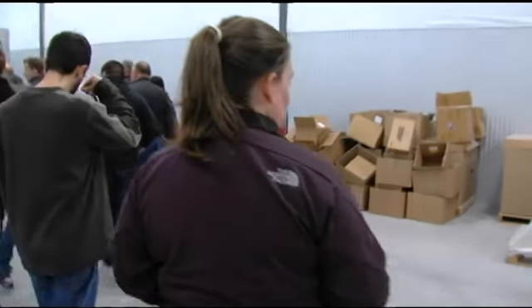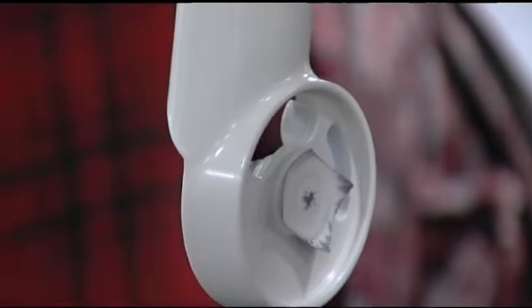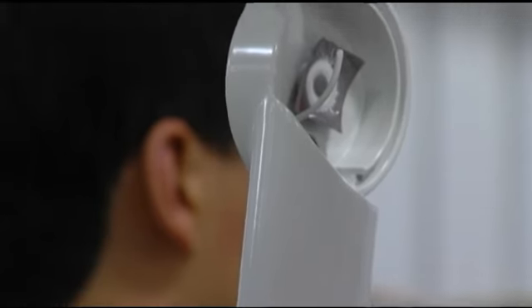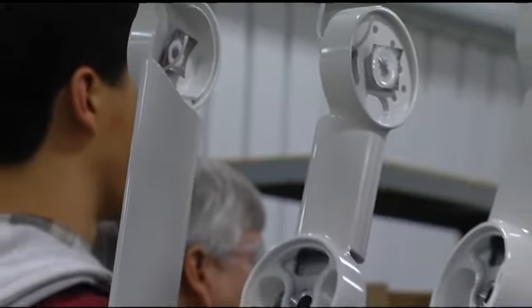First oven, we put outgassing primer on them. Then we cook them again. Then we sand them because we can see any holes, any issues, any surface problems once we've got the gray base coat on them. And then we top coat, a powder coat in white.